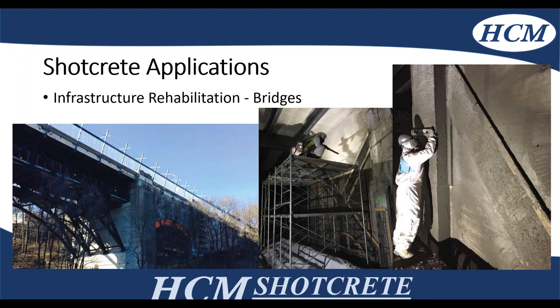On infrastructure rehabilitation, it's also been done on bridge work. This is an example of the Prince Edward Viaduct in Toronto. We worked with Toronto Zenith on this project and had a very small working window — four hours on evenings on Sundays — because the TTC rail was still active. This overall project took about eight days of work and saved immense schedule because we were able to rapidly place and repair all of those areas. We used a dry mix shotcrete with an accelerator for this project, with heating and hoarding to maintain the right ambient and substrate temperature.